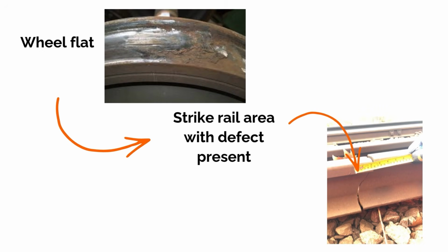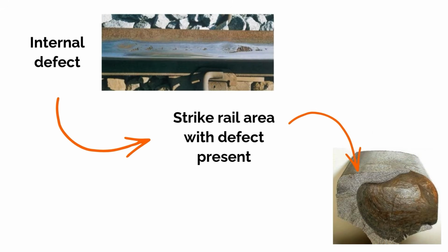A wheel flat, or damaged wheel, repeatedly strikes the rail. If that rail already has a defect, and the support is poor beneath it, the crack may grow faster, and eventually that wheel strike might be the thing that pushes it over the edge. An internal defect, subject to the heat of a nearby weld, grows. The sleepers in the area are already offering poor support, which leads to bending and fatigue of the rail, increasing the rate that internal defect grows, finally leading it to break the rail.